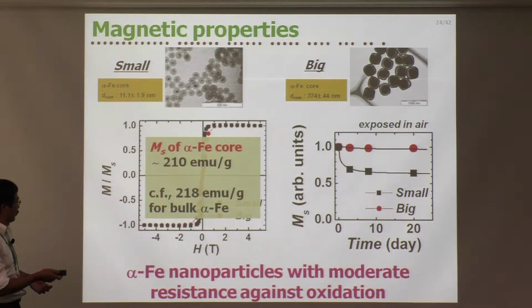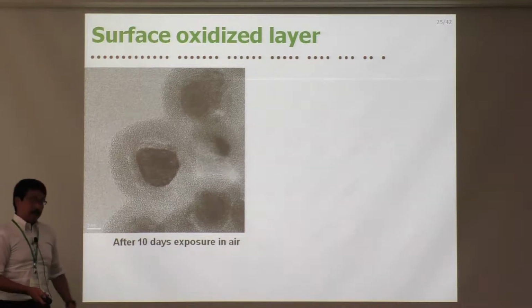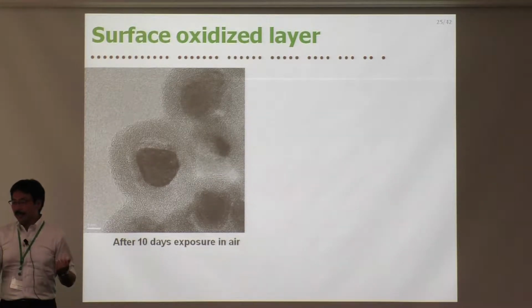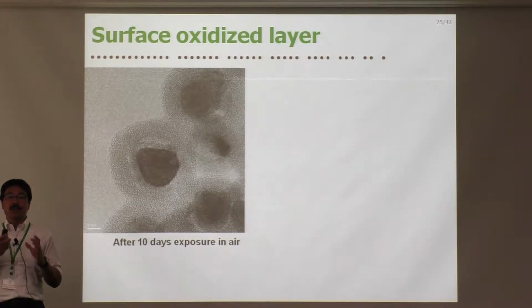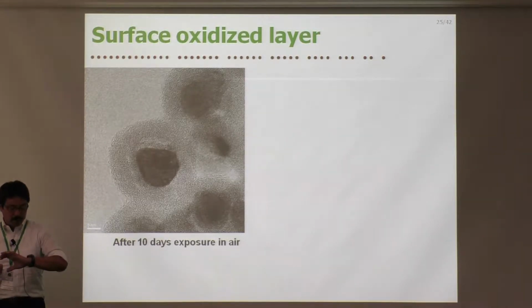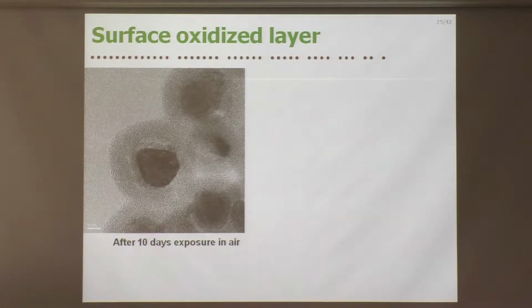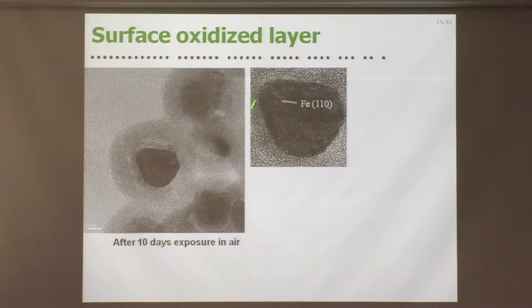In the previous slide, I said the surface of the nanoparticles are oxidized upon exposure to air. Here we checked the surface oxidized layer by means of high resolution TEM measurement. This shows the high resolution TEM image after 10 days of exposure in air. As this close-up view shows, we can see nice lattice images throughout the nanoparticles.